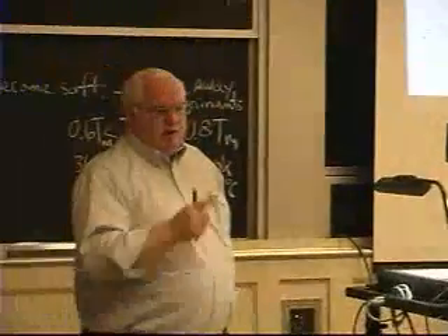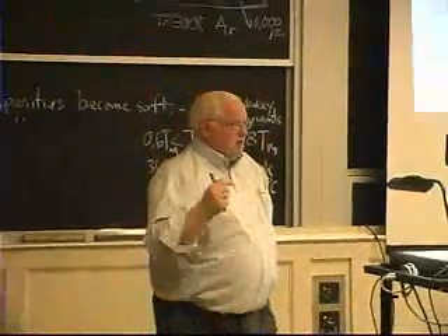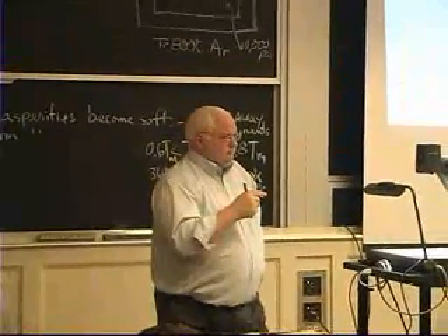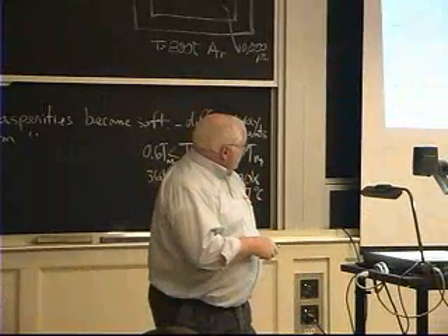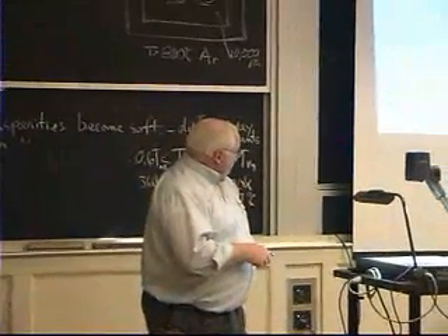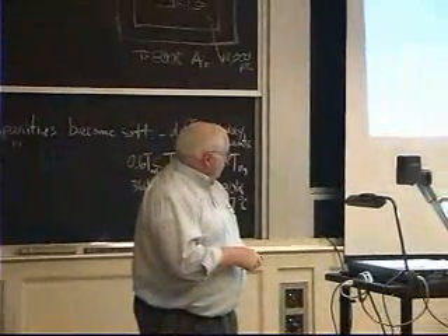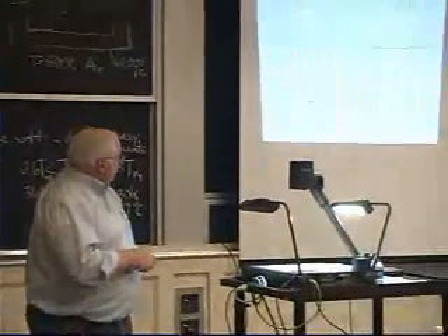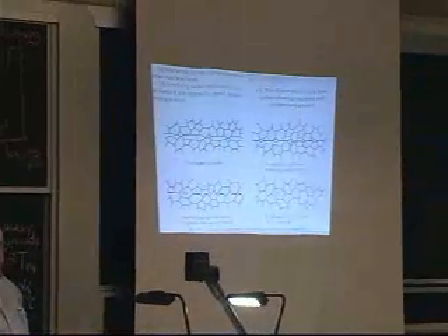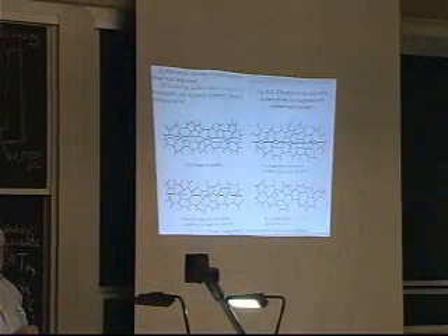It might be 10,000 lattice rather than 1 or 2 lattice that you have to diffuse through. Okay? And so you tend to get third stage volume diffusion pore elimination, which takes forever. So true diffusion bonding stops here in stage 2. If you ever get to stage 3, it's all over.